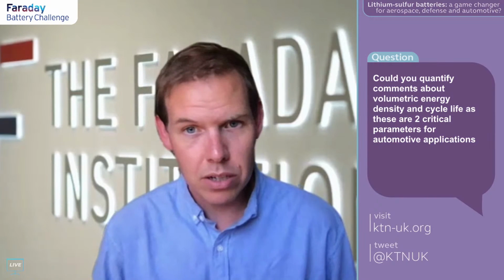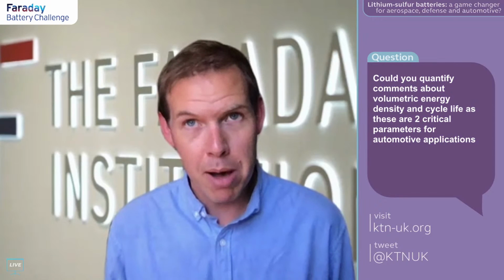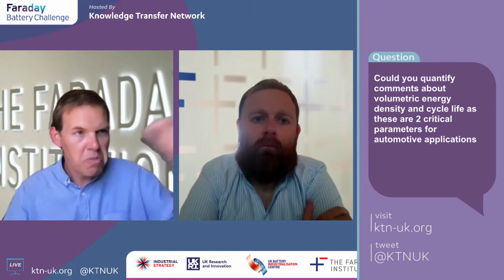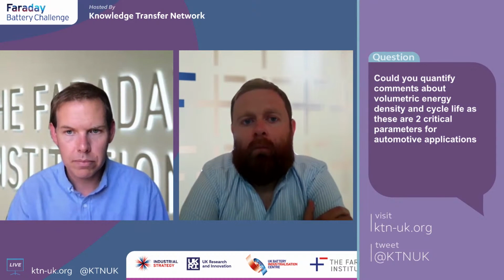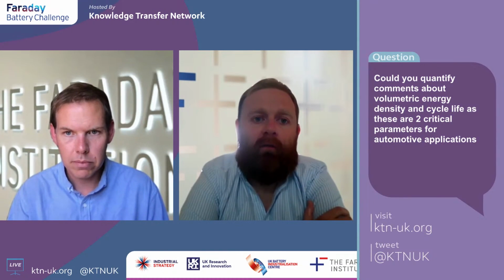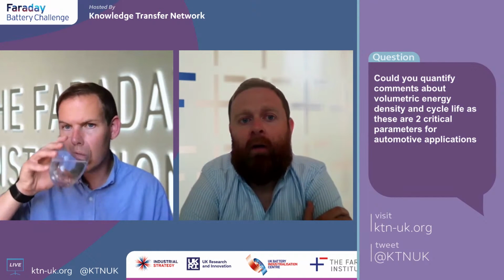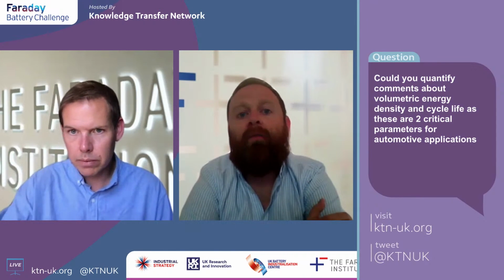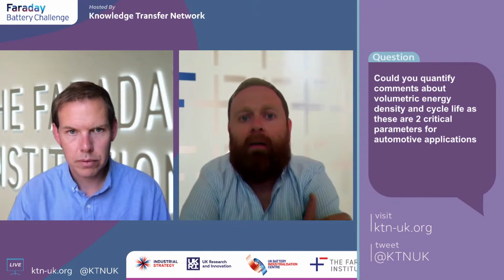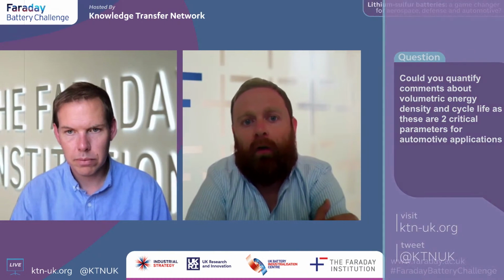If you look at current generations of lithium-ion cell, we are probably at about 200 watt-hours per kilogram and 700 watt-hours per litre. So I think the lithium-sulfur is naturally going to outperform on the gravimetric and underperform on the volumetric, but we're hopeful that we're targeting 500 to 600 watt-hours per litre and 500 to 600 watt-hours per kilogram. In a historical sense, the volumetric and gravimetric energy density have kind of coupled one for one. So as you add 50 watt-hours per kilo, you tend to add 50 watt-hours per litre to the overall target.